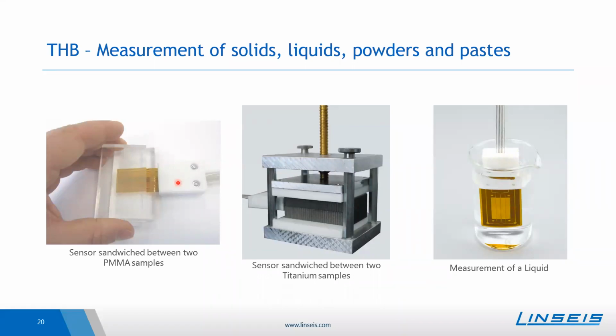The difference is that the 2 sample setup is more universal for lower to higher conductive samples and has the higher accuracy. The single-sided sensor is especially suited for the high conductive samples, as one can more easily realize the measurement of thinner metallic or high conductive samples.